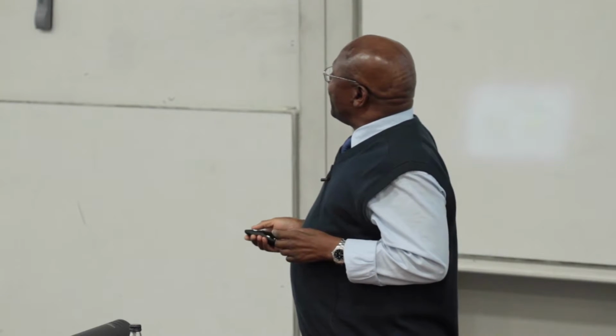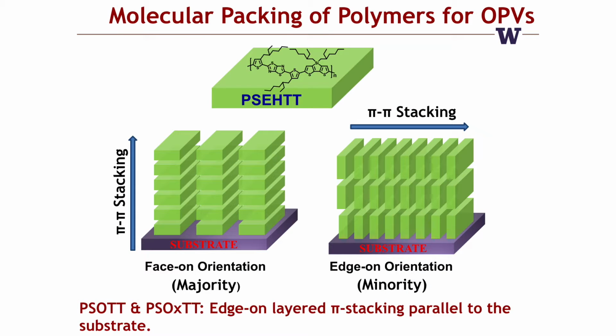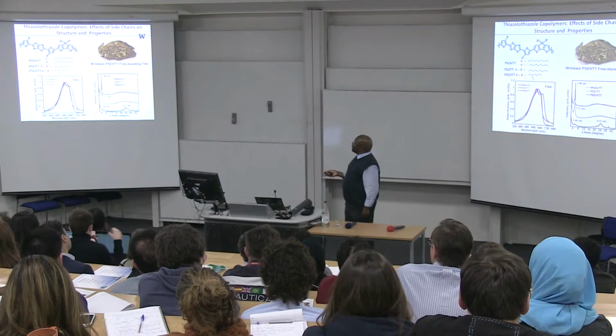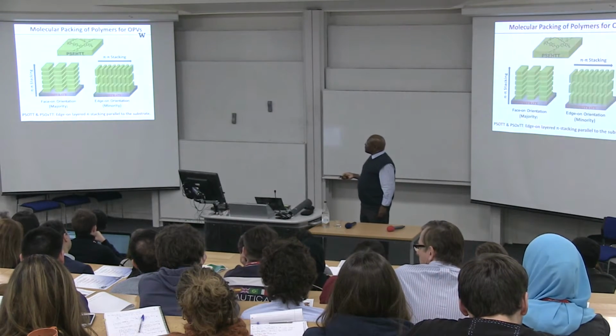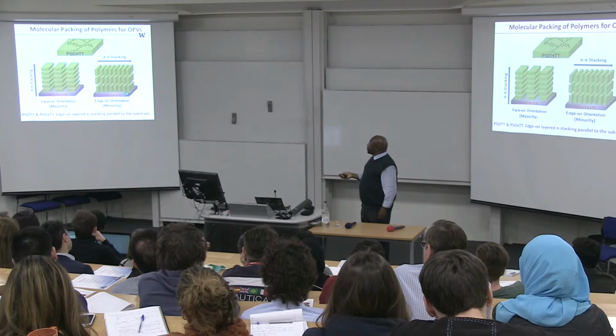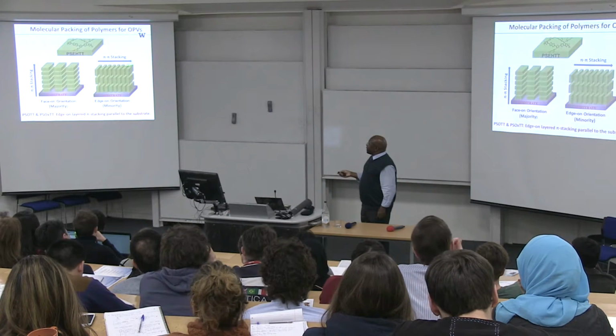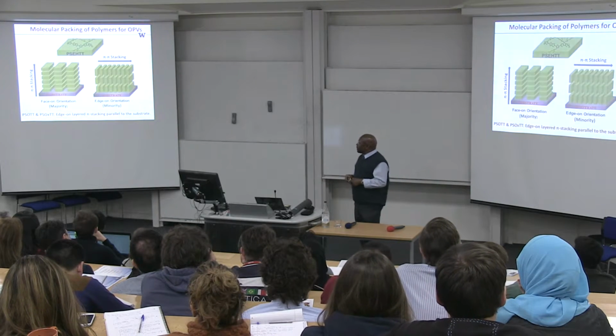And in fact, I show it here better, that in the case of PSEHTT, it tends to pack such that the molecule lies on the substrate and pi stacks like that, so that the pi stacking is perpendicular to the substrate, as opposed to the other two polymers with more linear side chains, where they pack edge-on, so that the pi stacking direction is parallel to the substrate.